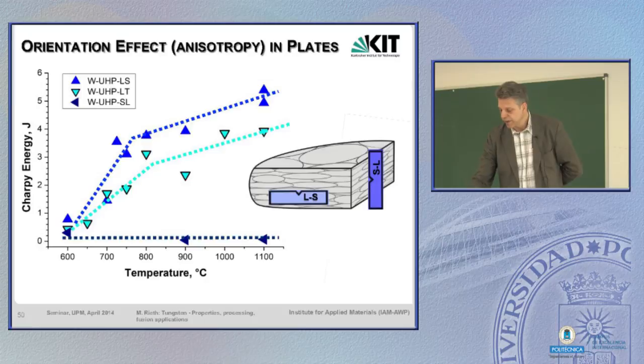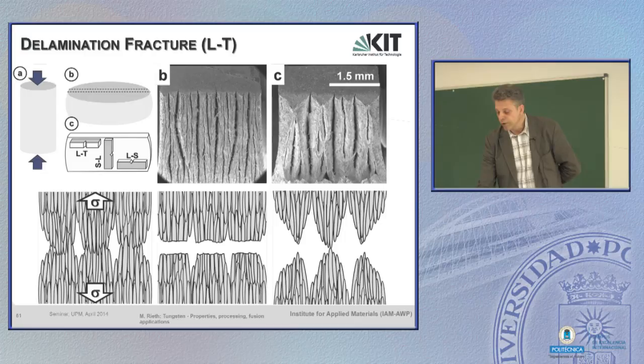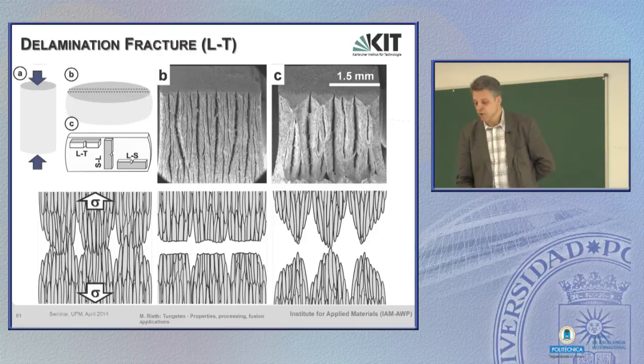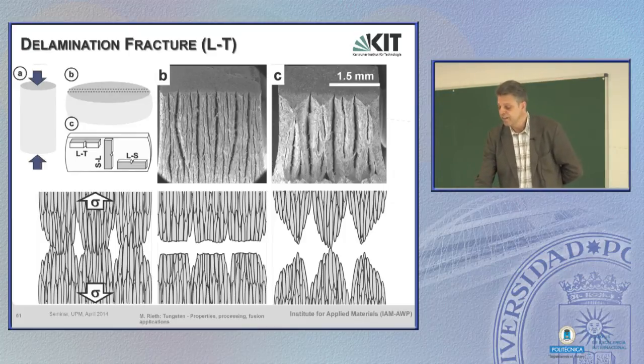If we rotate this specimen by 90 degrees, then the pancakes would be loaded in the second best orientation. And you see, if you load them through, then you see in the crack such laminar structures, which are due to plastic deformation, and this corresponds to this line. So indeed, in 2 dimensions, in the surfaces, we can load plates easily. That's not a problem, but we have to avoid this type of loading, this orientation.